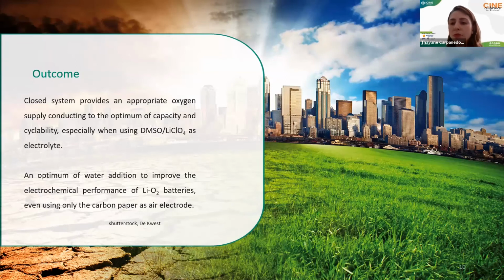So as conclusion of the results presented here, we bring that the closed system provides an appropriate oxygen supply, conducting to an optimum of capacity and cyclability, especially when using DMSO and lithium perchlorate as electrolyte. And we can go even better with water addition, and so we can promote better discharge capacity and cyclability, even using only carbon paper without any electrocatalysts.